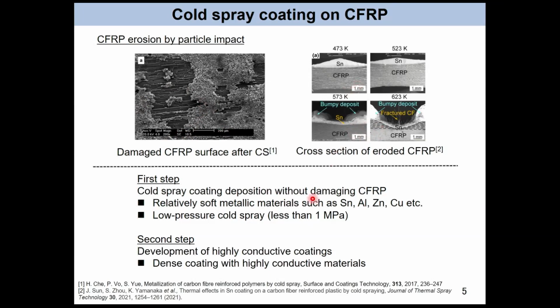So when applying this cold spray technique to CFRP coating, first we must consider cold spray coating without damaging the CFRP, especially the carbon fiber. Normally, relatively soft metallic materials such as tin, aluminum, zinc and copper are suitable for deposition. Also, cold spray is normally separated into two types, high pressure cold spray and low pressure cold spray. Low pressure cold spray has a pressure under 1 megapascal. This limited velocity is suitable for coating on CFRP. And after that, the second step, developing a highly conductive coating, for example using copper or other good conductive materials, is important.